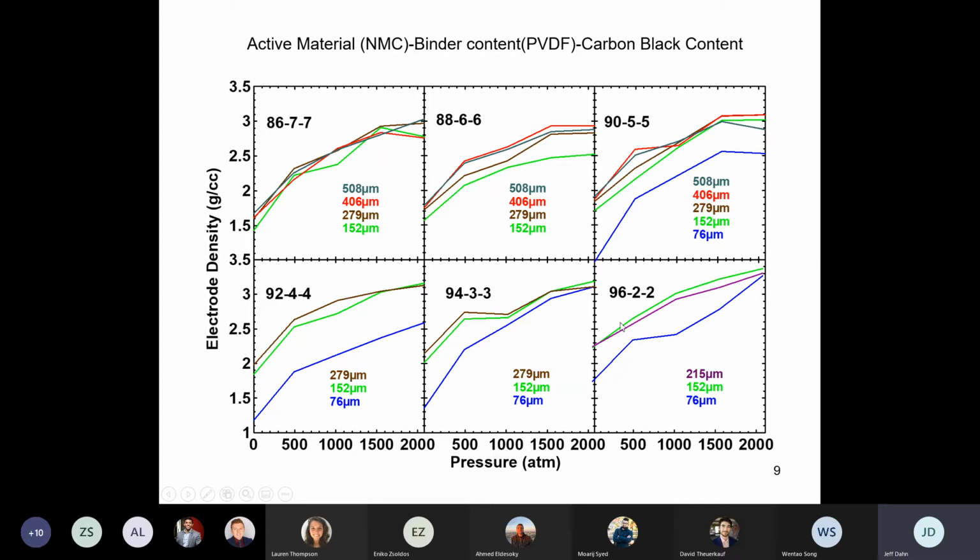And that allows you to pack more material into the cell, and that's going to give you a greater energy density. So what does it mean relative to the electrode porosity? NMC 111 has a crystal density around 4.7. So if you just worry about the electrode material only, the filling fraction would be 3.3 divided by 4.7, and the porosity would be 1 minus 3.3 divided by 4.7.